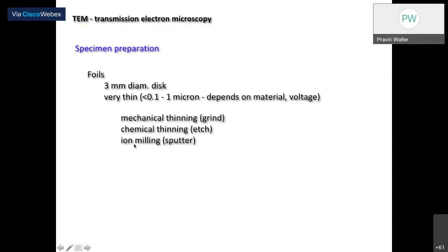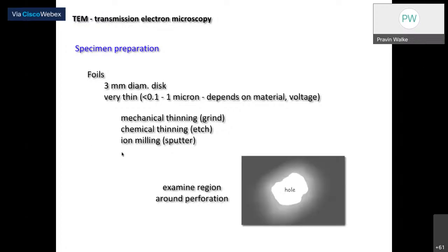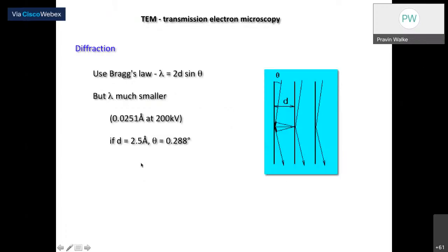For example, they use grinding, then etching, then ion sputtering. This is the ion sputtering image of the thin film. You just make a hole and tilt your sample to find out what is happening at this edge, so that you can understand the thin film information at this particular region. So this is another important specimen preparation.